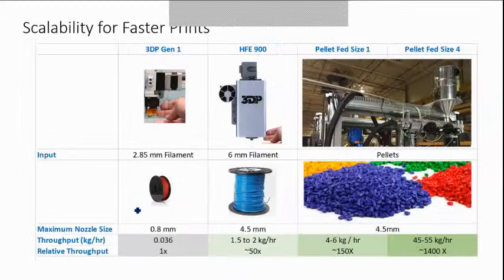And it comes in different forms. In this printer, we directly use a pellet. We don't use the wire only. We can use a wire, but we can also feed the pellet directly like in injection molding and can print in large quantities. You can go as much as about 4 to 6 kilograms per hour.